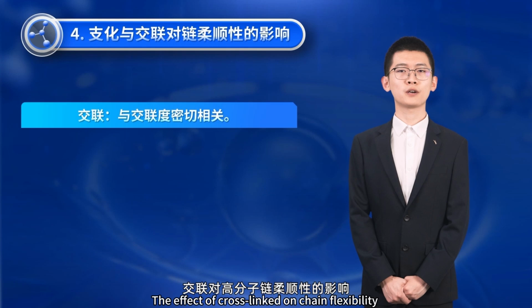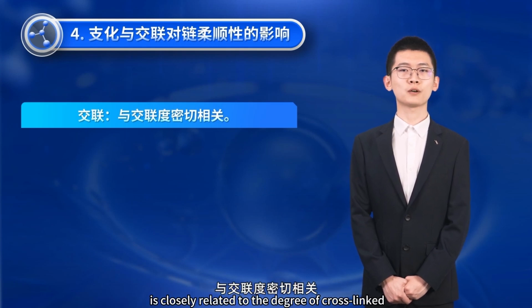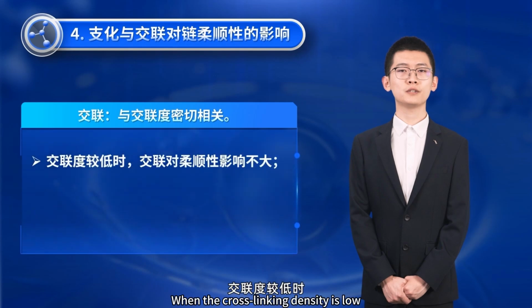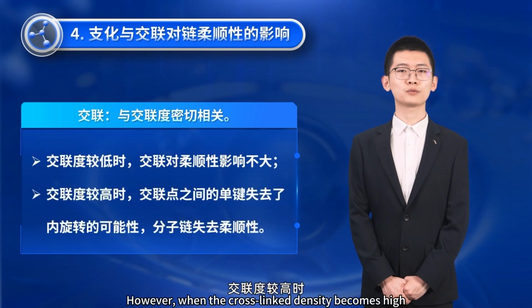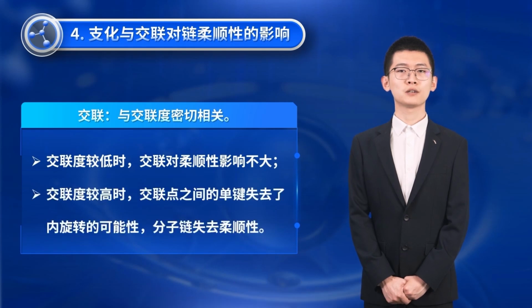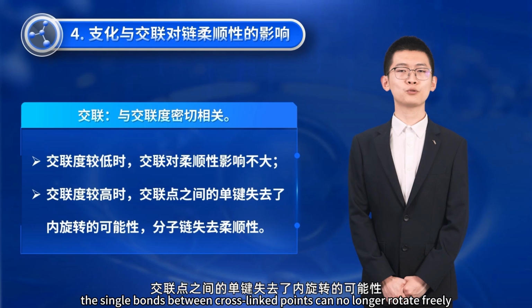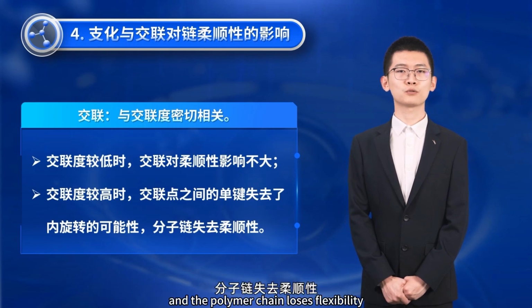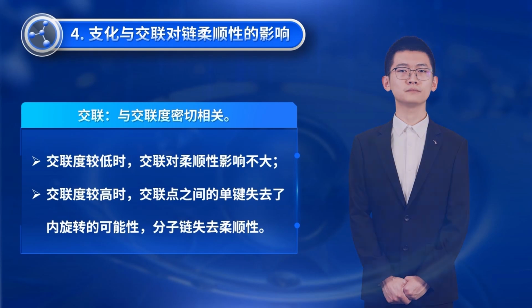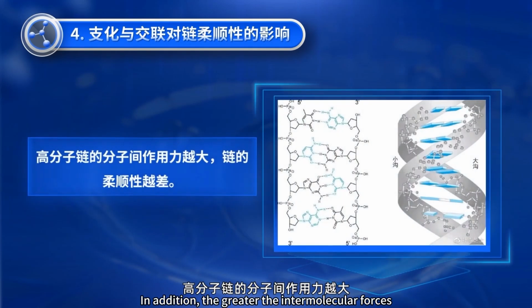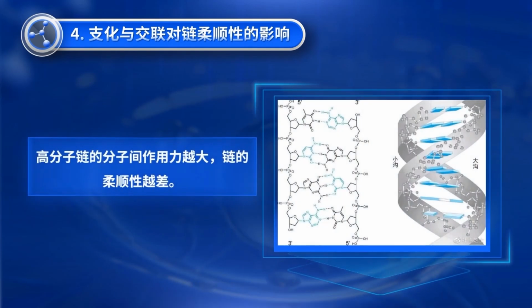The effect of cross-linking on chain flexibility is closely related to the degree of cross-linking. When the cross-linking density is low, the impact on flexibility is minimal. However, when the cross-linking density becomes high, the single bonds between cross-linked points can no longer rotate freely, and the polymer chain loses flexibility. In addition, the greater the intermolecular forces, the lower the flexibility of the chain.